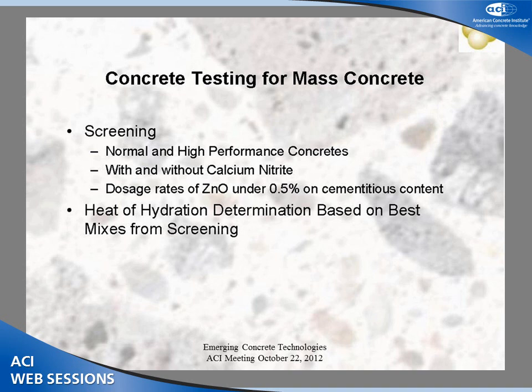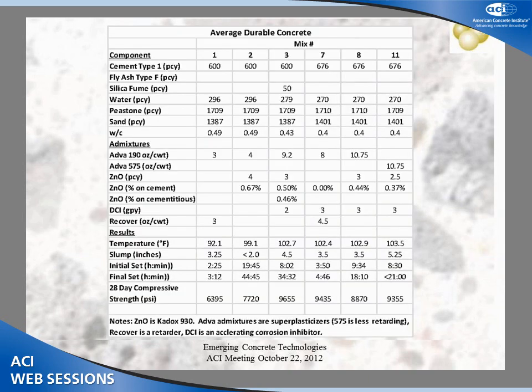So, looking at zinc oxide for use in mass concrete, I'll go into some of the concrete mixtures. We looked at both normal durability type of concretes and high-performance concretes, both with and without calcium nitrite. And this time, the dosage rates of the zinc oxide were kept under 0.5%, because we already know what type of retarding effect we get when we're above 0.5%. And so the mixes that were chosen for the actual adiabatic heat of hydration work were based on the best mixes that came out of the concrete screening. So this is a very busy slide, but just to try and navigate through it, I wish the pointer was working a little bit better. There we go. If we look at the first three mixes, the cement content, these were all produced with a Type 1 general purpose Portland cement.